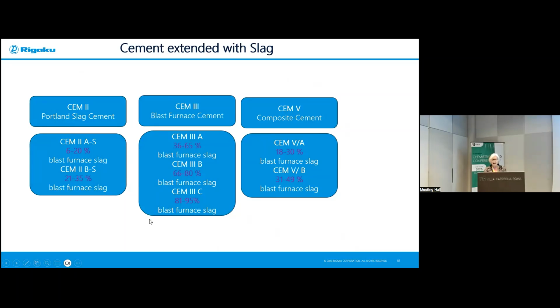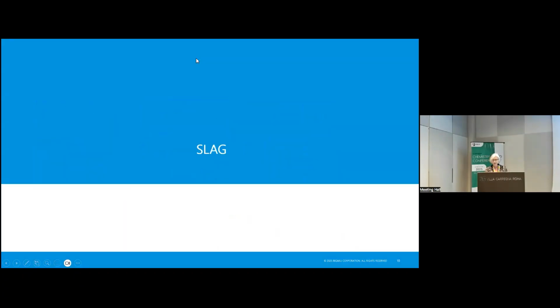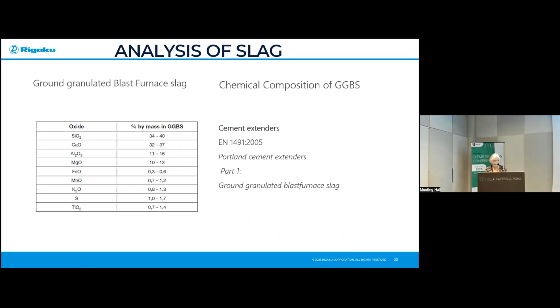But in order to add this blast furnace slag, we need to make sure that it conforms to the conformity, right? Because if it does not conform to the conformity, we will not be able to use it in the extension of our cement. So it's very, very important and very critical that we accurately and precisely measure the slag before we make these blended cements or extended cements with the slag. So let's look at slag. How do we do the conformity testing of slag?